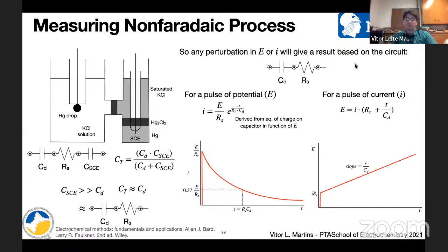Let's consider now a pulse of current. So you have the cell at open circuit potential, and then we apply a current, and now you are measuring a potential. So you're measuring potential over time. We have a jump of potential from the equilibrium potential to a potential that's equal to current times resistance, because this is time 0, right? So you won't have this part of the equation.